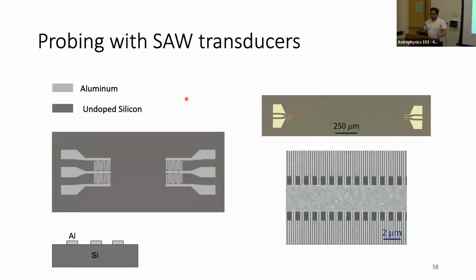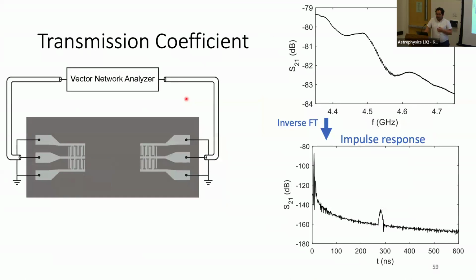In order to test this, we made a surface acoustic wave transducer. We made IDTs of aluminum directly on silicon. Normally you would say this is a terrible idea. This should not work, and we thought it would not work actually. We made the surface acoustic wave launcher and receiver, and then we measured the S21.